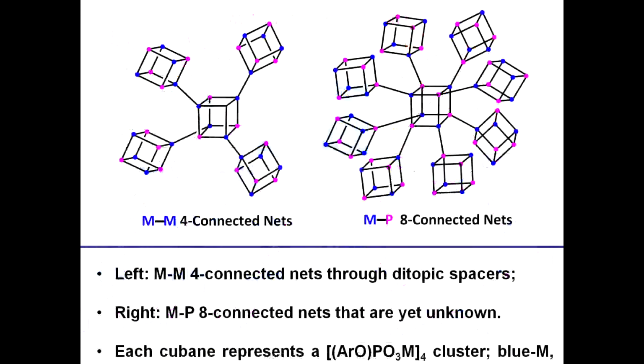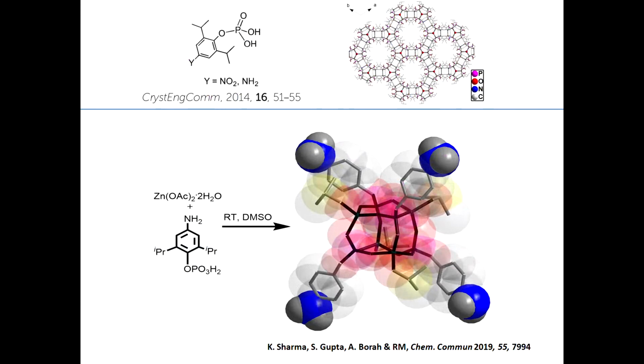And that's when Kamna came along, and she did some very interesting modification. I think she had some organic chemistry background from Jaipur. She said we'll put a functional group in the para position. It's essentially the same molecule which I've been using for 7-8 years. So she nitrated the phenol and then reduced it to the amino. And then essentially the same structure that I published about 2007, 2008, but the only thing is now I have 4 amino decorations. So the amino immediately throws up 2 possibilities.